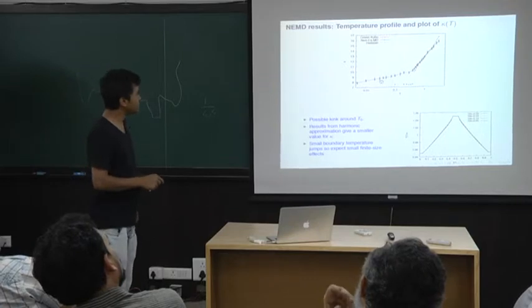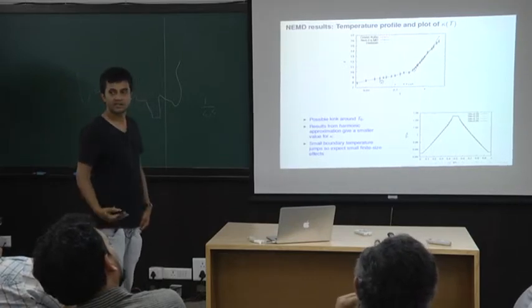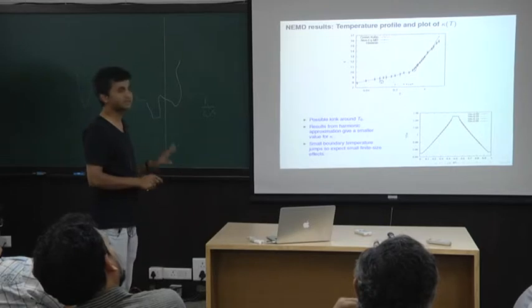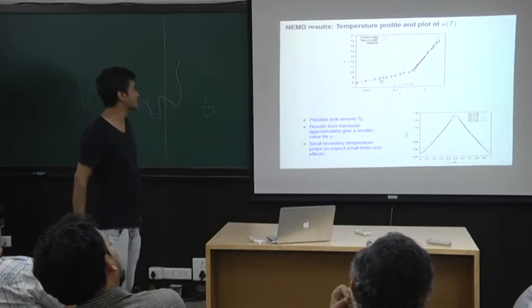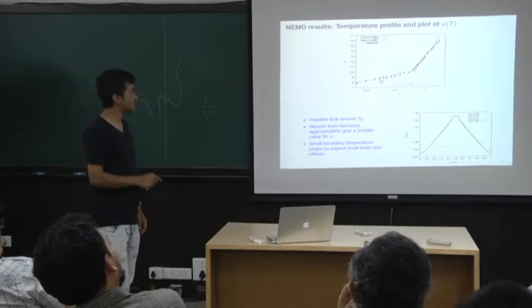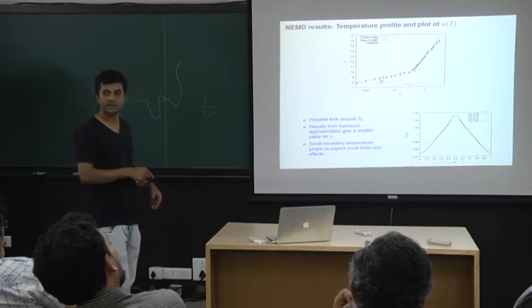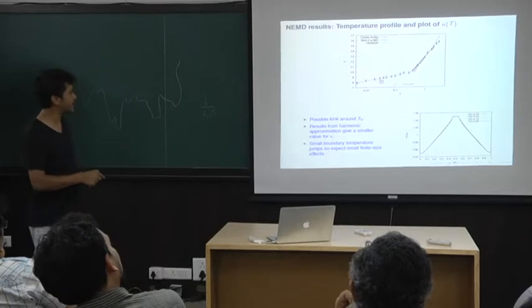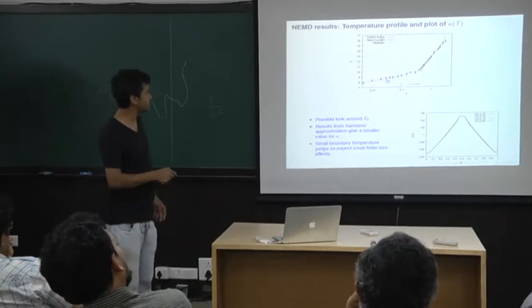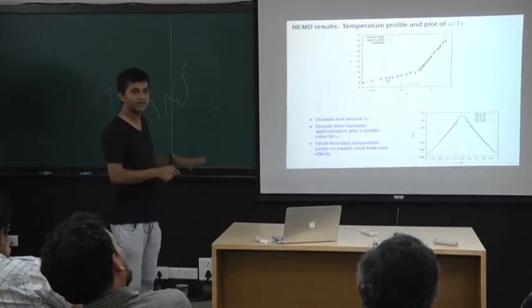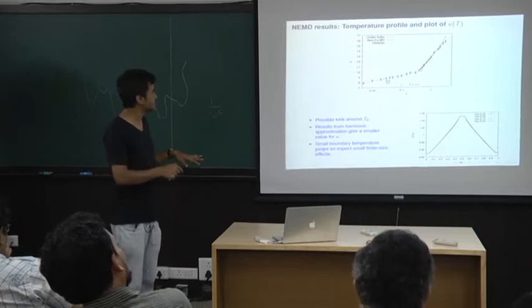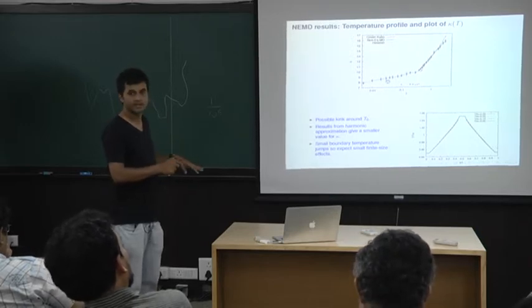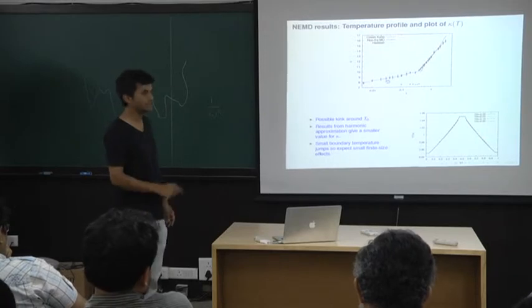Here what I show is what we get from this Green-Kubo calculation. I should say that this is still not complete. What we are trying to do is the Green-Kubo and the Hessian calculation and make sure that everything is fine. But right now it looks like this. The thermal conductivity you get from the harmonic approximation is much lower than what you actually get from the direct simulations.